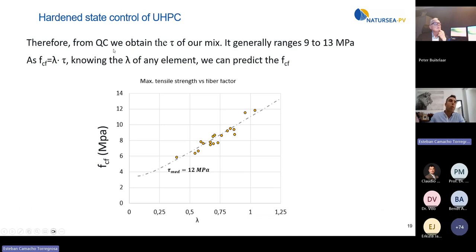And now that we obtain in the quality control the post-cracking tensile strength, and we know the fiber amount that we have, we can obtain the bonding strength tau, this constitutive parameter to design, which generally ranges for UHPC mixes between 9 and 13, depending on the fiber content, the cement content, the capacity of the mix, and so on. But it does not depend on the fiber content or the fiber orientation. This is the key. When we know this bonding strength, we can predict for any element where we know the fiber amount the post-cracking strength.